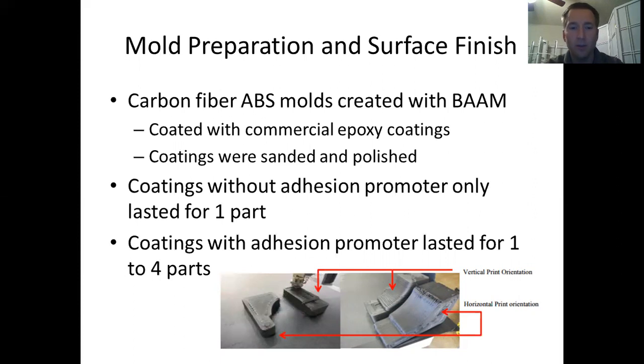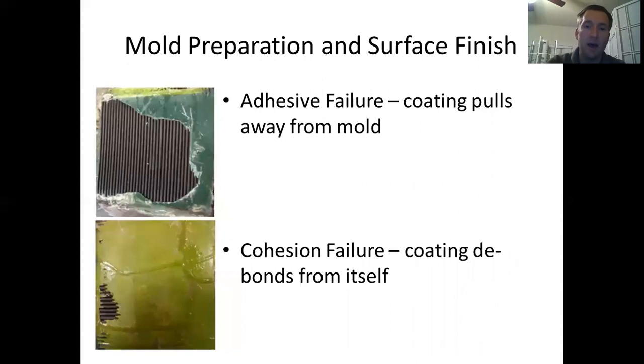And then with some of the other coatings, they used the adhesion promoter, and they were able to make 1 to 4 different parts out of that same mold before the coating was damaged to the point that it wasn't usable. So here's an example of that damage. The top one is considered an adhesive failure, and that's where the coating pulls completely away from the mold. And the bottom one is considered a cohesion failure, where the coating comes apart from itself, and you're left with spots without coating, and it becomes uneven, and depending on your application, it may or may not be able to be used at that point.